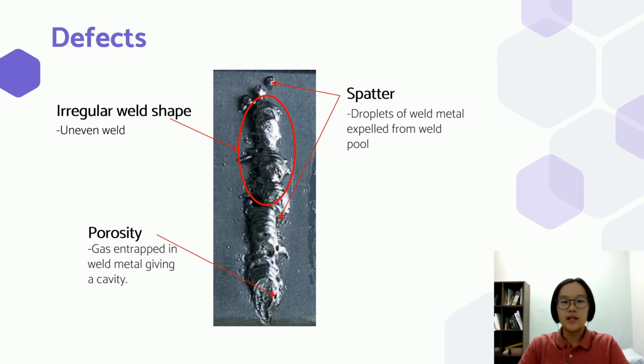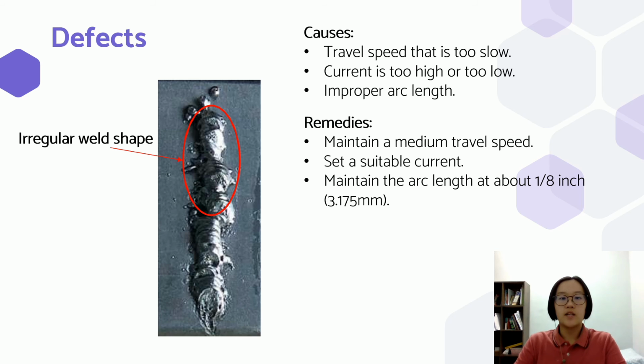There are 3 defects observed in this weld bead. First, irregular weld shape, which means uneven weld. Second, porosity, which is gas entrapped in weld metal giving a cavity. And third, spatter, which is droplets of weld metal expelled from the weld pool. I will explain each defect starting from an irregular weld shape.